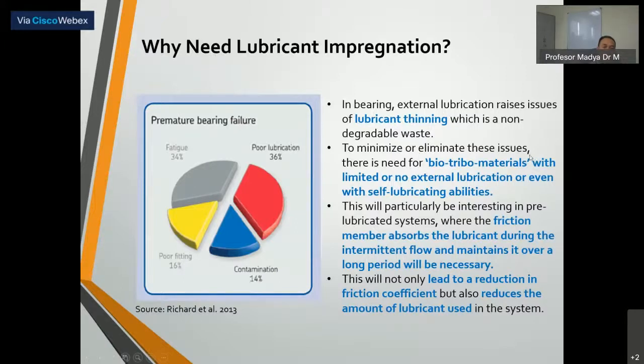To minimize or eliminate this issue, there is a need for biotribological material with limited or no external lubrication, or with self-lubricating abilities. That's why we use the term lubricant impregnation. It means that we impregnate the lubricant into the voids of the composite itself. This will particularly be interesting in pre-lubricated systems where the friction member absorbs the lubricant during the intermittent flow and maintains it over a long period. This will not only lead to a reduction in friction coefficient, but also reduce the amount of lubricant used in the system.